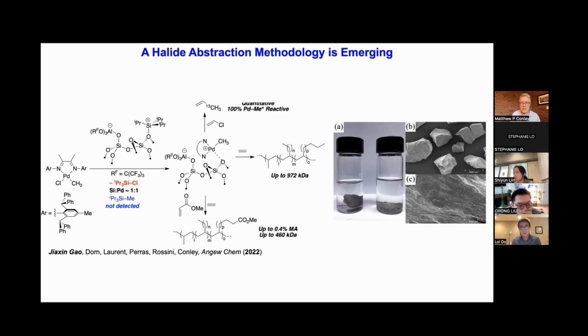So I suspect what we're seeing in that bimodal molecular weight property of these polymers is just related to the local chemical environment of the palladium site. We do know that the polar monomer is incorporated in the highest molecular weight fraction and the lowest molecular weight fraction, so we don't have a bias there. But that's something we haven't figured out how to really engineer in yet, how to control that to make these more bimodal, less single site, more single site.